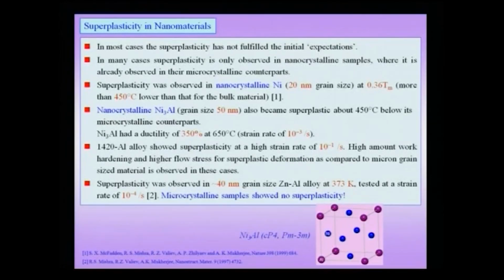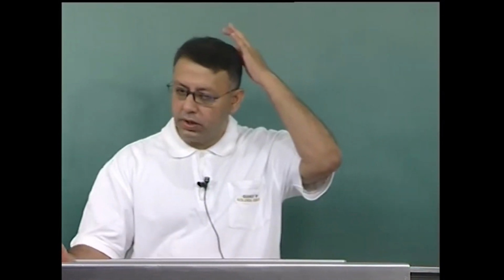We had made a lot of observations regarding superplasticity in nanomaterials, and we had also noted previously that superplasticity in some sense is a very closely related phenomenon to creep, except that in superplasticity damage accumulation does not lead to failure, and therefore you are able to get very long tensile elongations of the order of 350% to 2000%. This gives us a beautiful mechanism, whereby by superplastic deformation we can obtain nice shapes and use it as a nice production method.